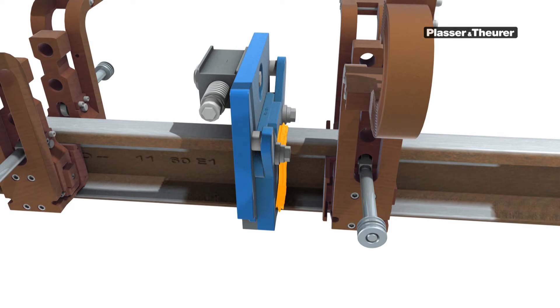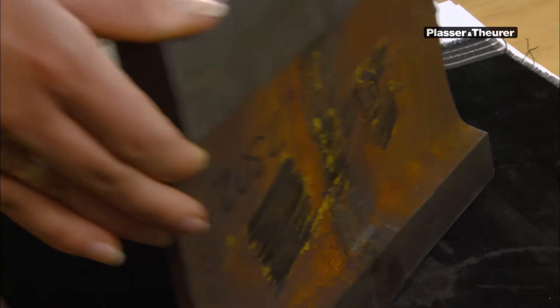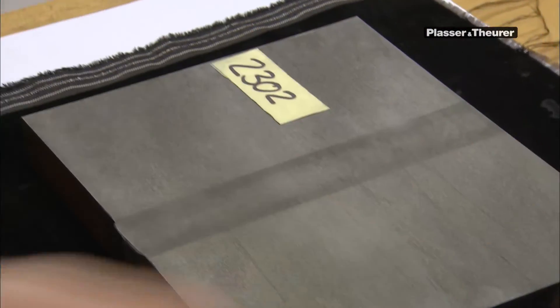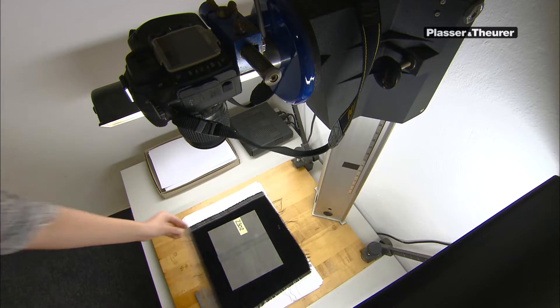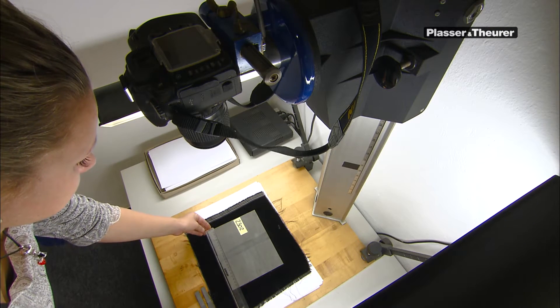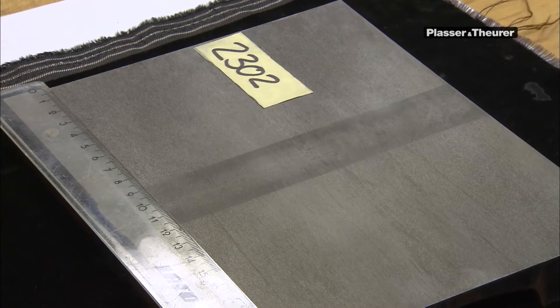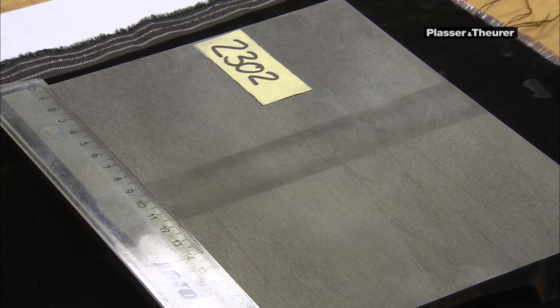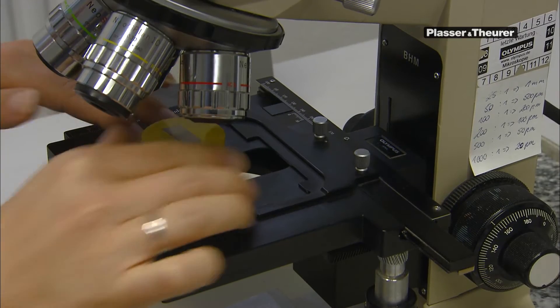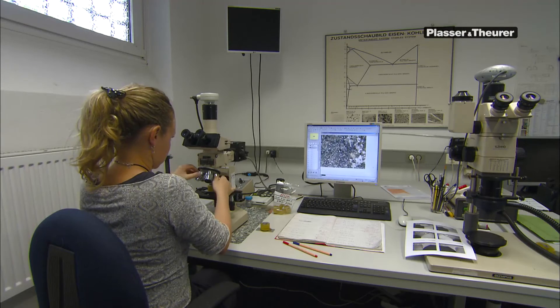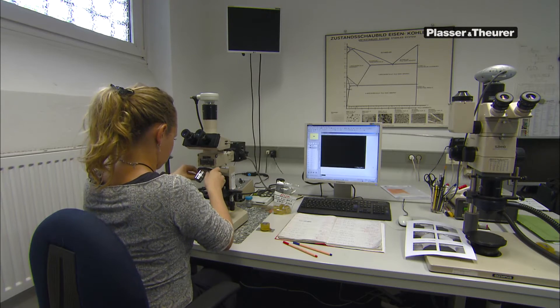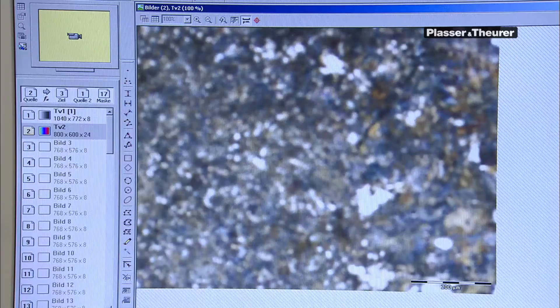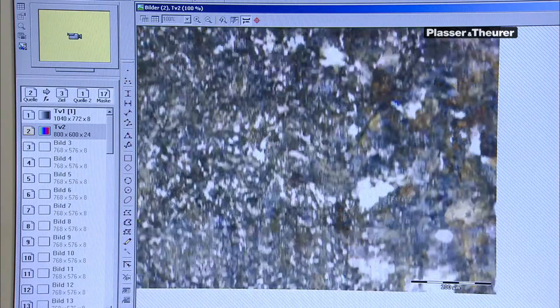Straight afterwards, the upset metal is trimmed off. The welding quality achieved is unequalled. Because no filler metal is used, the weld is completely homogeneous without any significant interruption in the hardness curve of the rail. The method allows the formation of the important characteristic crystalline structure in the rail material.